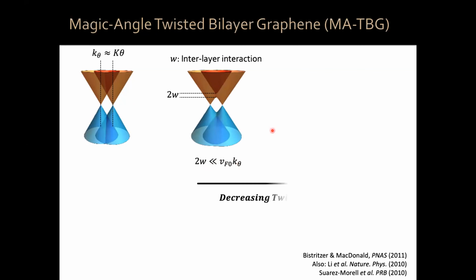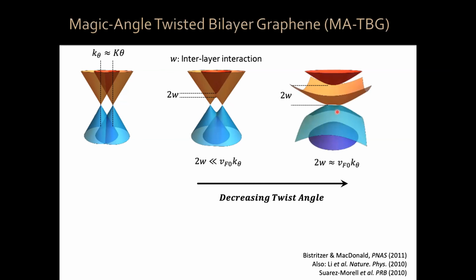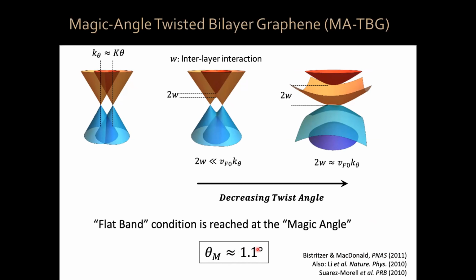Okay? If you now decrease the twist angle, you can see that these 2 cones, these 2 crossing points will get closer and closer to each other, and this bonding state will get lower and lower in energy until you reach a condition where that lower band goes down to 0. You reach something which is known as the flat band condition, okay? This flat band condition is reached at the so-called magic angle, and famously then, but now very famously, Rafi Bistritzer and Allan MacDonald predicted this magic angle to be 1.1 degrees back in 2011, okay? And there was also interesting simultaneous experimental and theoretical work at the time.